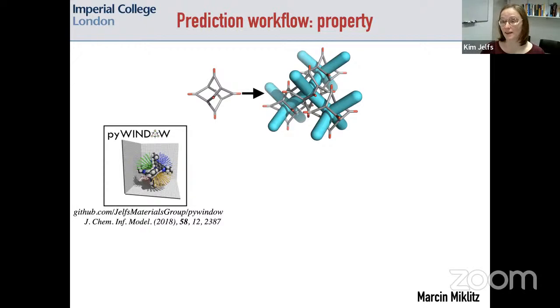And something that's critical for us is that it's computationally cheap enough that we can run that analysis over a molecular dynamics simulation. Because while we're simplifying it by looking at the molecular level, we know it's really important to consider the flexibility and the breathing motions of that host porous material. But if we run a molecular dynamics simulation on a single molecule, we can get what many people call a pore limiting envelope. So basically a histogram of the different void sizes that that host molecule can adopt, when you factor in thermal breathing effects, and also we can do it with guests present, so you can see cooperative behavior where guests might open up pores more as well.